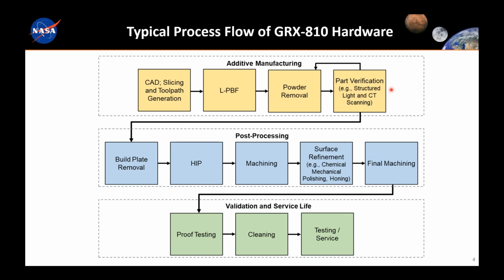Now, sometimes we will go through a stress relief depending on the component geometry, and then we do removal of the build plate. GRX 810 we've processed in 2 conditions. You can HIP the material, and you do get improvements in fatigue life that Tim showed in one of his slides, but we also can process the material and use it in the as-built condition, meaning that there's no heat treatment on that. Typically, we will use it in the HIP condition, again, just because we get improved fatigue life and some improvements in other properties as well.